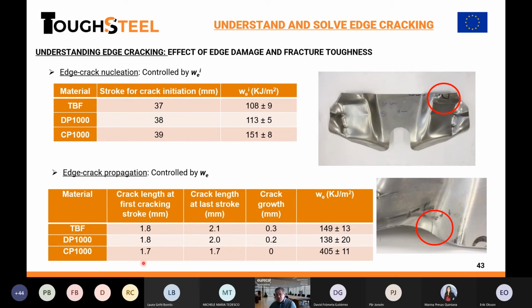And the clear case is this: in the complex phase steel, remember in the last slide, high toughness, the crack almost has no change. So when it appears, even if you keep on deforming, even if you keep putting energy in the system, the material can withstand the growing, and produces this effect. So I think this is an important concept. Initiation is for initiation, and total energy explains what happens when the crack is fully developed.